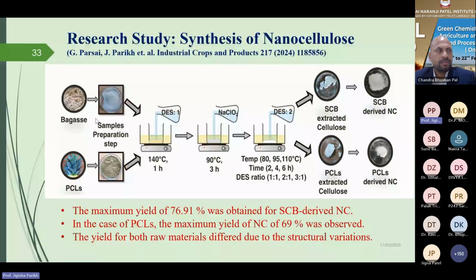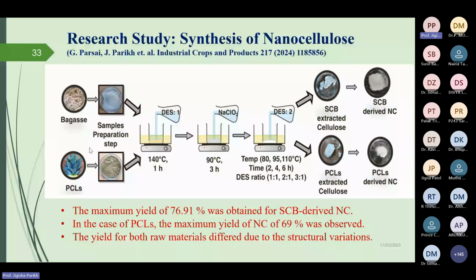So here we have obtained a maximum yield of about 77 percent from the sugarcane bagasse, and in case of the pineapple crown leaves, we have received about 69% of the nanocellulose. So as I said, because of the structural variation, the yield will be different. So you have to identify what possible yield can be derived from this, and accordingly apply the typical pre-treatment as well as the post-treatment method. Either you can go for a one-step process, or a two-step process. Combination of various pre-treatments, multi-parameter pre-treatment, also is possible.